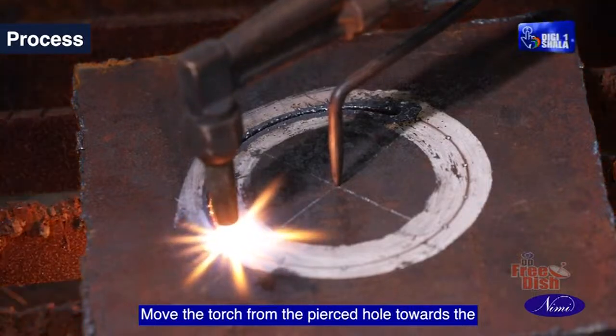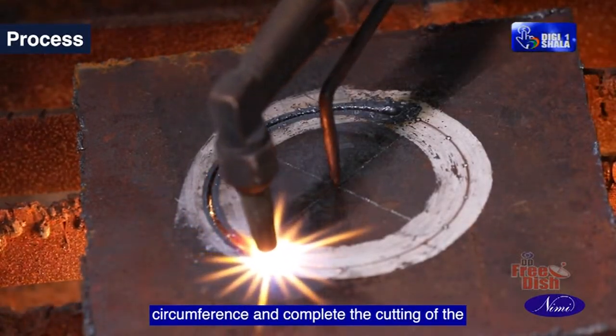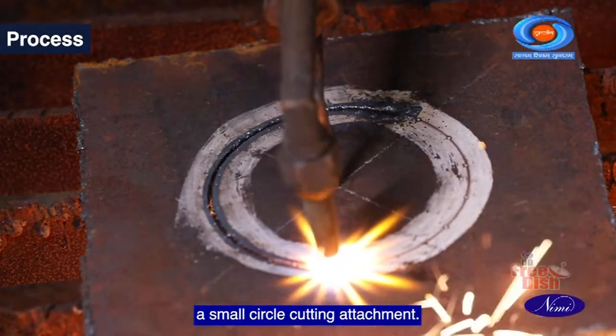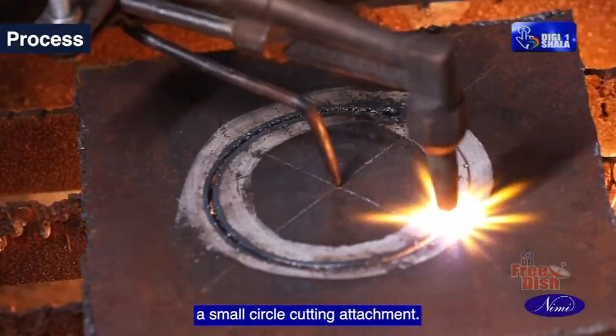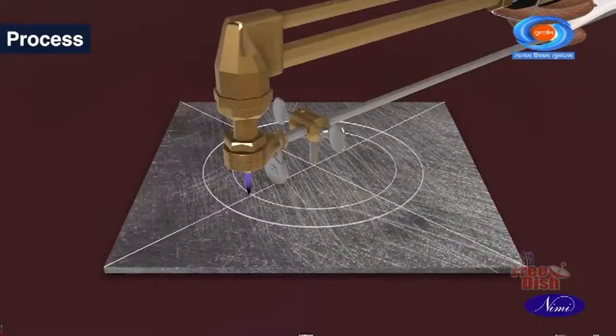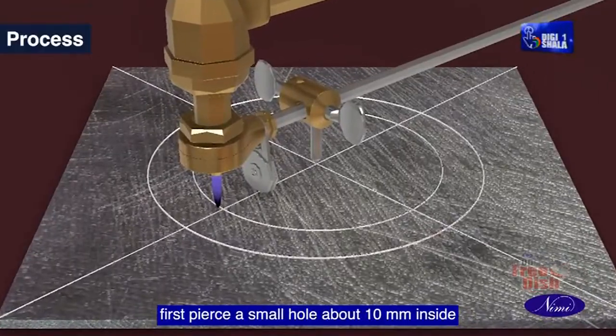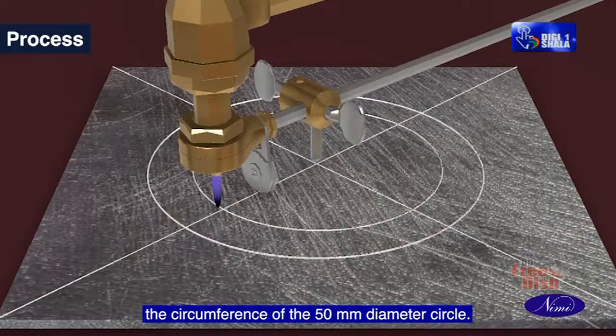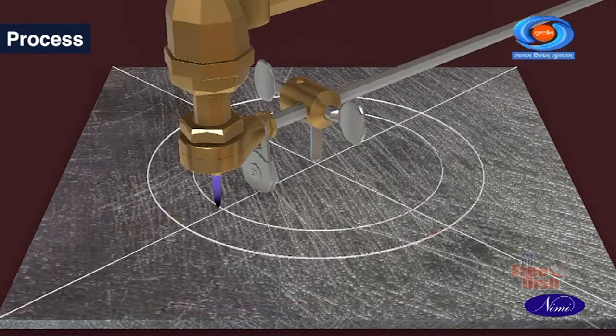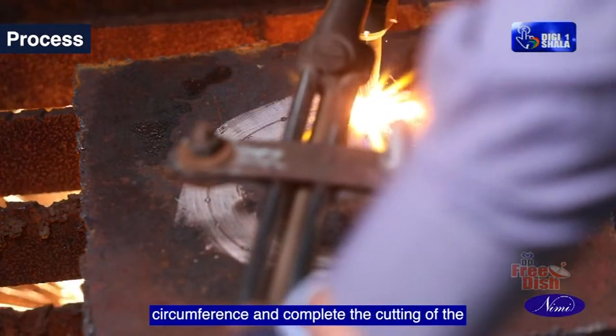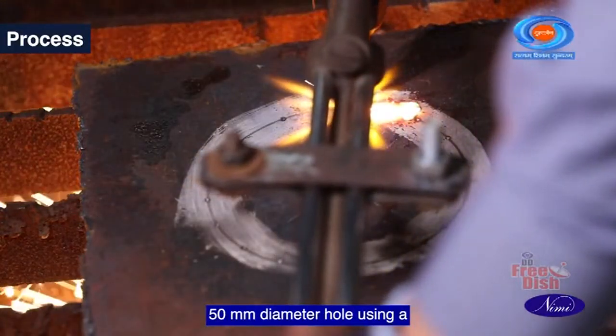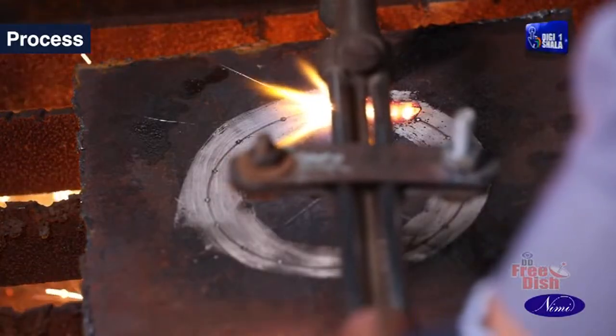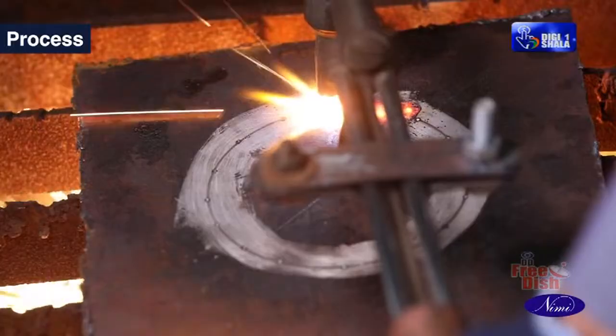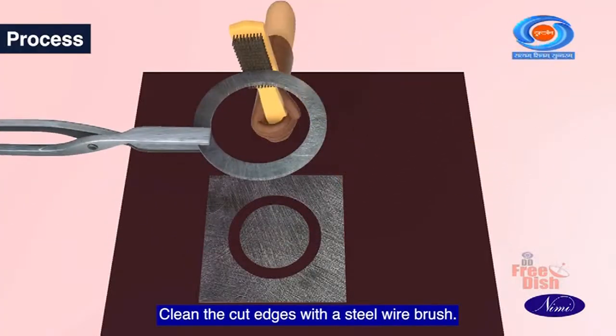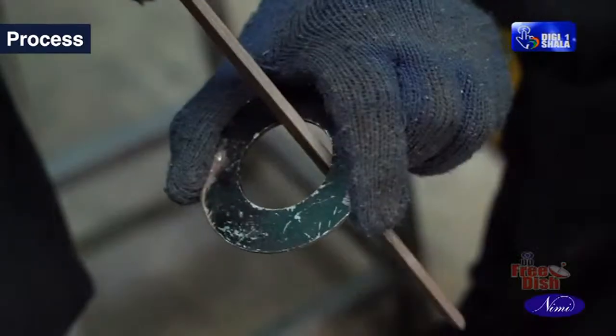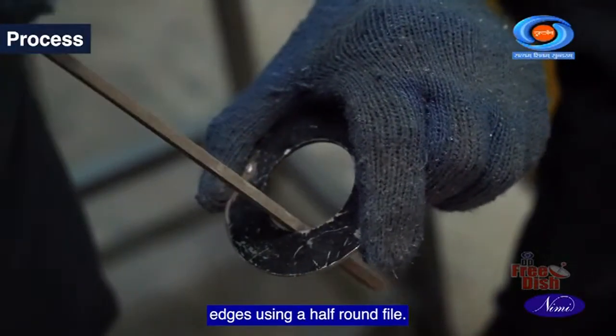Move the torch from the pierced hole towards the circumference and complete the cutting of the 50 mm diameter hole using a small circle cutting attachment. To cut the internal circle, first pierce a small hole about 10 mm inside the circumference of the 50 mm diameter circle. Move the torch from the pierced hole towards the circumference and complete the cutting of the 50 mm diameter hole using a small circle cutting attachment. Clean the cut edges with a steel wire brush. File the inside face of the cut edges using a half round file.